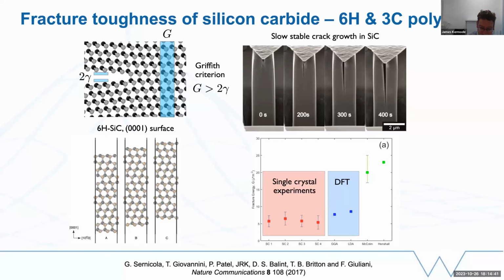just resynchronize a bit. Previous experiment shown in green. There we go. Get the laser pointer going again, which were not as carefully aligned and didn't correctly measure the single crystal fracture energy. So if we want to make a quantitative connection, and we can identify the relevant quantity and carry it out in a small periodic system, then DFT is fantastic. But it's very difficult for understanding the dynamics or the kinetics of these processes.